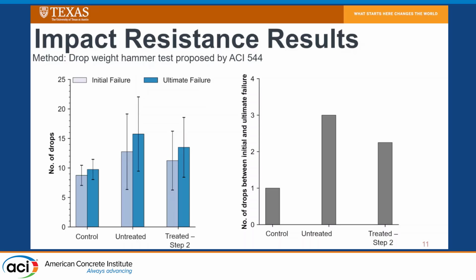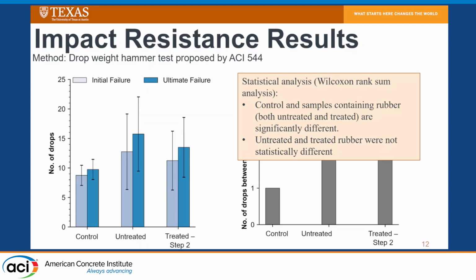The other thing that you can see with this method is that there's a lot of variability, right? We see a lot of overlap with these error bars. So we also did statistical analysis in order to see whether this was actually statistically significant. And the end result of that is that our control samples, so the samples with no rubber, and the samples containing rubbers, are statistically different. However, when we look at the difference between treated and untreated rubber, they're essentially similar in terms of performance with respect to impact resistance. So what this means is that the inclusion of the rubber is making a difference on impact resistance, right? However, whether it's treated or not, it doesn't really make a big difference here. That is what this is saying.